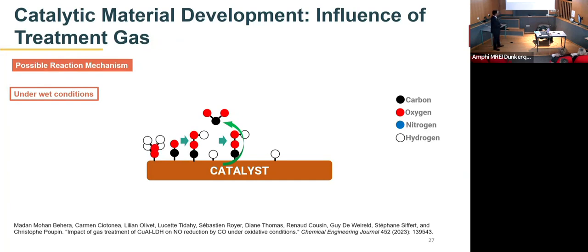atomic hydrogen on the surface of the catalyst, which can react with the nitrogen monoxide from the gas phase to form the OH, that is the hydroxyl group on the catalyst surface, and an atomic nitrogen. This atomic nitrogen can again interact with another atomic nitrogen which is near to it in order to form the dinitrogen. This is why we see NO reduction activity under the wet reaction condition, and this mechanism is a water gas shift-like mechanism, because we don't see a release of hydrogen in our experimental data.